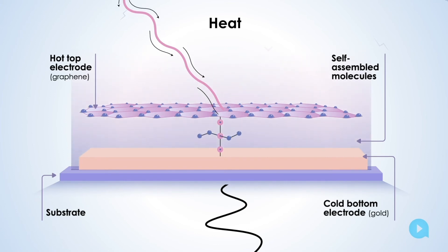If we put something heavy, such as side chains, on the molecule, then the wave of vibration gets reflected there and much of the heat will go back to the hot side.